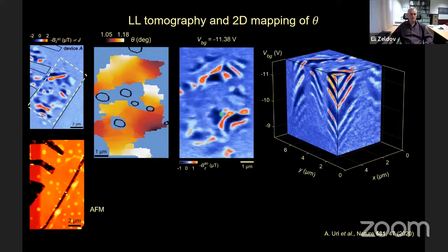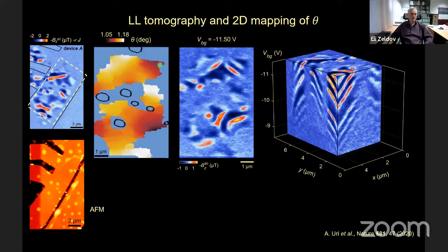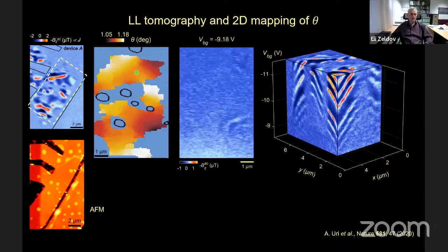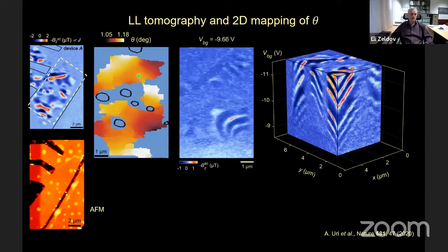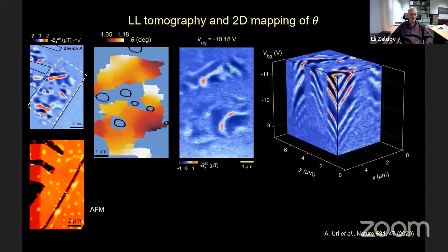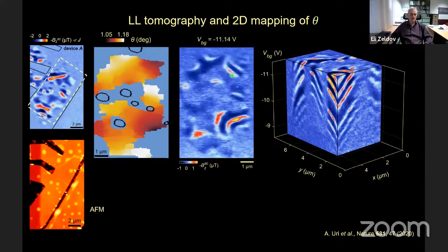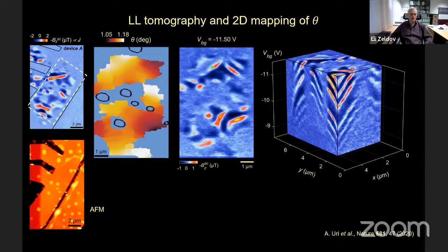curved shapes. If we look at this region, we have two minima. So Landau levels should form here and form here. And we have a saddle point. So the Landau levels will form at these two points, reach the saddle point, split and move in opposite directions. So you see Landau levels merging and splitting, merging and splitting in opposite directions. Here's another pair coming, merging and splitting.